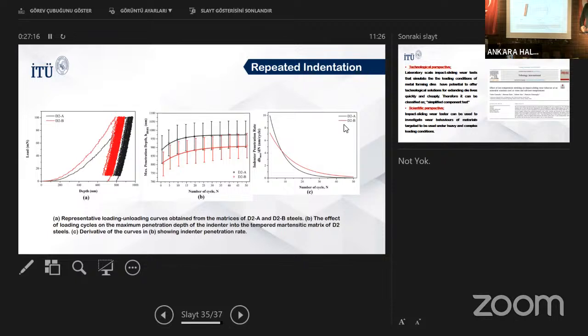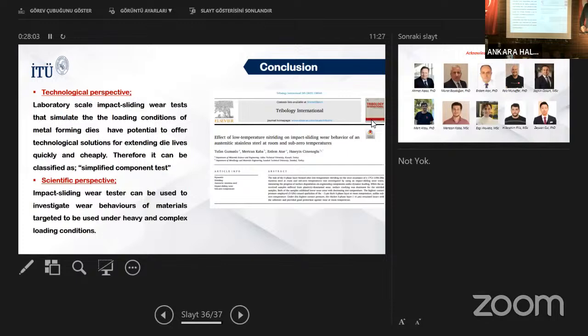Then we take the slope. After taking the slope, we can quantify the softening. Okay, this one, the red one, was the one which has got finer carbide. So the red colored one is the one containing the smaller carbide. The rate of softening in this one is low. So finally, this one, the fine carbide containing one, is expected to exhibit longer service life if the die material is made of this D2 grade. So those are the conclusions.